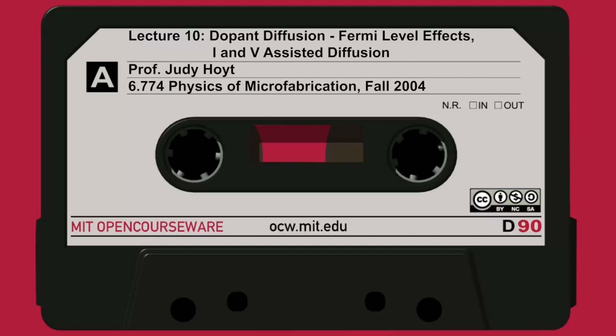Well, again, people could say that this high concentration of phosphorus is pumping interstitials because P and I are diffusing together, so that the interstitials themselves are being carried in towards the base. We get a high supersaturation of these interstitials. They get released when the phosphorus stops diffusing, and they're released into the boron base. This excess of interstitials then enhances the boron diffusivity and causes it to push in, because we know that boron has an F sub I of 1. So this is an interesting effect.